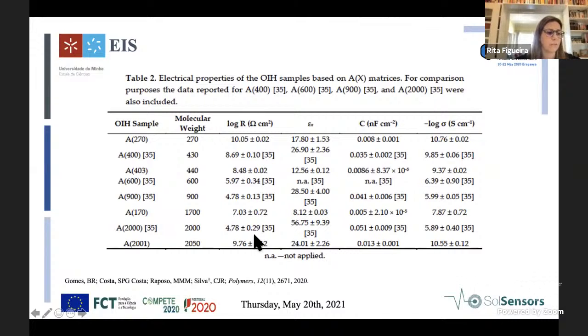There's a difference for A270 compared to A400, and this may be due to the fact that the RFD 270 contains an aliphatic amine containing both rigid cycloaliphatic and flexible heteroamine segments within the same molecule. So this may explain these differences. Because in previous studies that we performed with similar products that establish the same type of bonds, you see that as the molecular weight of jeffamine increases, the resistance decreases. And this is directly connected with the content of organic component. So it's something that we expected to obtain.